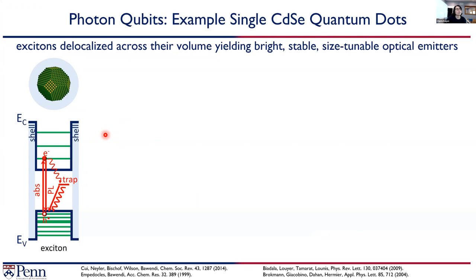compositions of semiconductors that have been made, often when there was a core and just the ligand shell, we appreciated them for their bright excitonic luminescence. But bright was still something often at room temperature of about 10%, where you could both excite and get luminescence from the quantum dot states. But of course, the surface presented dangling bonds that could create trap states that would limit the quantum yield. And so I'll show you examples, but also by overgrowing a shell like you would in quantum dot heterostructures, you can get near unity quantum dots.